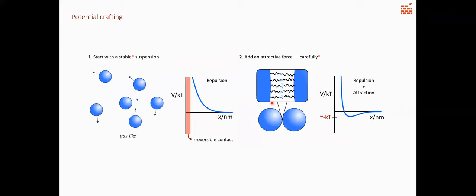And so there's a lot of ways that we can envision doing this, but I find that this is a very useful general guideline for how to program self-assembly. And the first important step is to make sure that your suspension of particles is stable. So what we saw in the last video was that we had particles diffusing randomly, kind of looked like a gas and they do behave like a gas in a lot of ways. And they have a kinetic energy of about kT and they're going to move all around their environment. So you actually don't have to worry about them finding each other. They will collide. But we have to actually be concerned what happens upon collision because if two colloidal particles make contact, that contact is irreversible. They're never going to break apart. That's because van der Waals forces are so strong. And so if everything aggregates and is stuck, then those particles can't reconfigure and explore their energy landscape and form an ordered material. And so what we have to make sure of is that there's some repulsive force that says, as two particles approach one another, some repulsion takes over that says this is not favorable. And then the particles diffuse away.